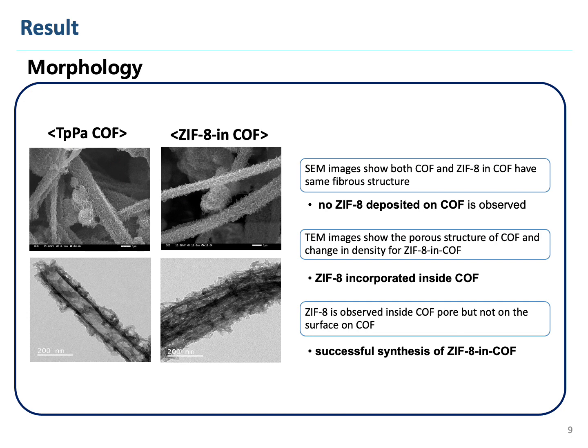Next, let's look into the result of the research. First is the morphology. The left side is the SEM image and TEM image for TPPA COF, and the right side is the SEM image and TEM image for ZIF-8 in COF. The SEM images show both COF and ZIF-8 in COF have the same fibrous structure, thus no ZIF-8 deposited on COF is observed. Next, TEM images show the porous structure of COF and a change in density of ZIF-8 in COF, from which we can know that ZIF-8 is incorporated inside COF. Furthermore, ZIF-8 is observed inside the COF pore but not on the surface of COF. Therefore, successful synthesis of ZIF-8 in COF can be concluded.